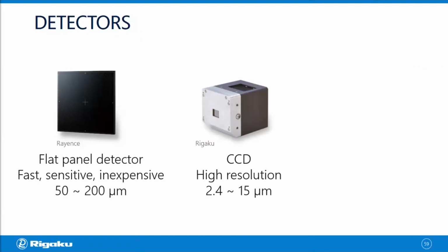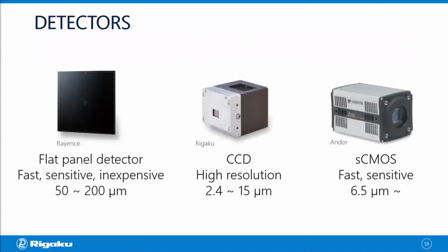Nowadays, the CMOS, or I should say sCMOS detectors, are available with pretty small pixel size, like this one from Andor that comes in 6.5 micron pixel size. And by using those sCMOS detectors, you're not compromising on the resolution that much, but you can make the scans quite a bit faster. So for faster scan, high resolution scan, the sCMOS detectors would work better than the CCD. And those are the three major categories of detectors.